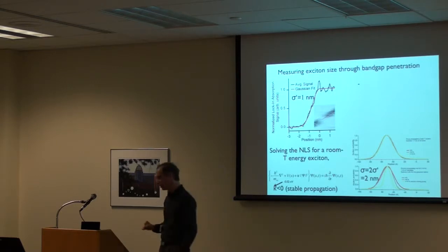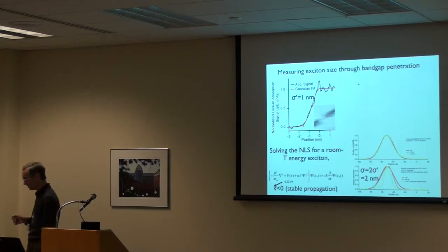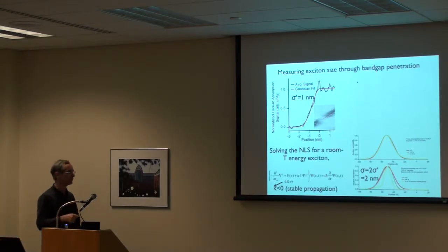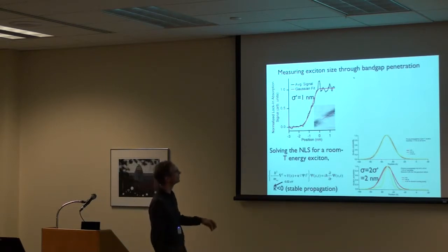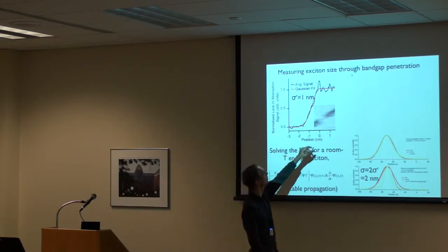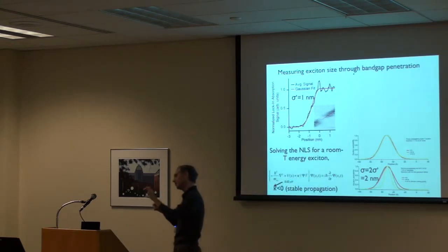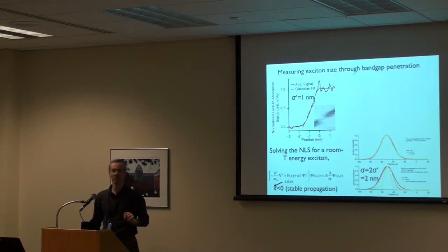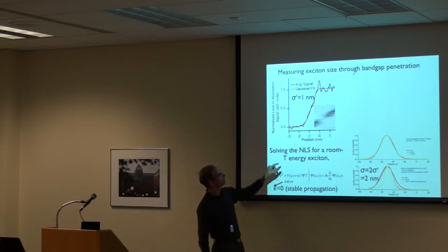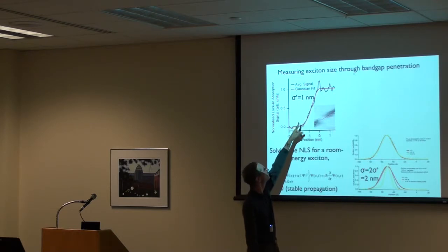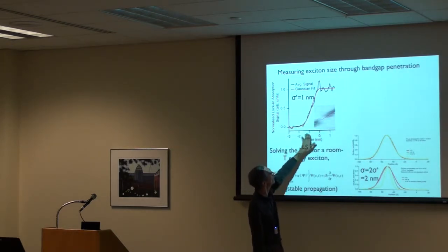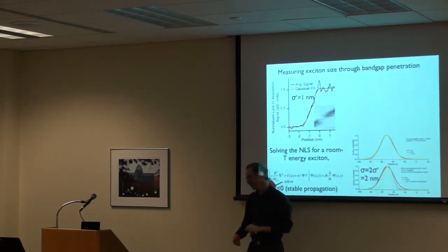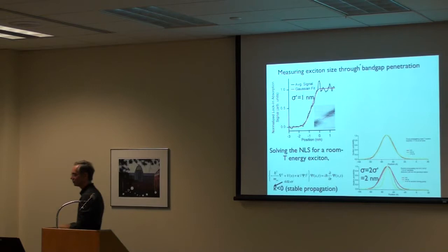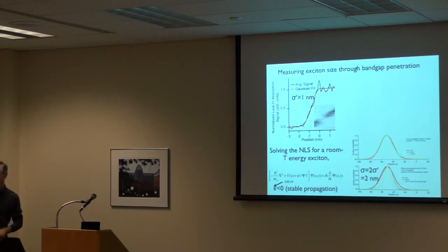It turns out it's pretty clear now, and I'm not going to get into all the details, that in carbon nanotubes you have exciton excitations by the kind of optical excitation that we're doing here. These excitons can move around the carbon nanotube, but they can't penetrate into that smaller band gap because of the energy mismatch. By solving a Schrodinger equation and comparing it with our measured rate at which this decays along the axis of the carbon nanotube, we were able to determine the size of that exciton, which turned out to be 2 nanometers in diameter. The theory for this particular carbon nanotube had predicted 1.6 nanometers, but I would say that's pretty good agreement between the two.